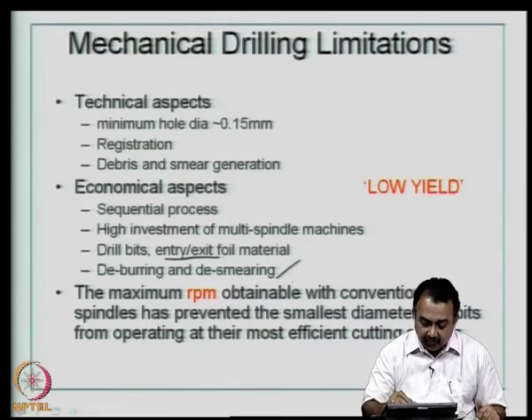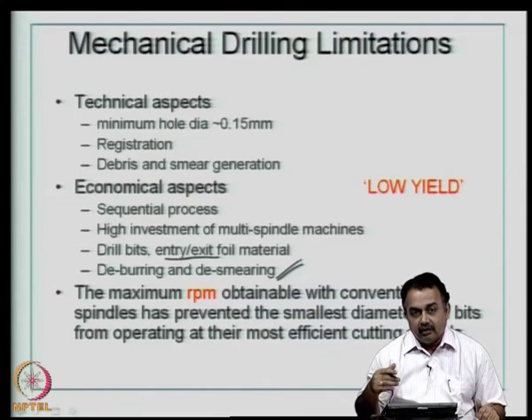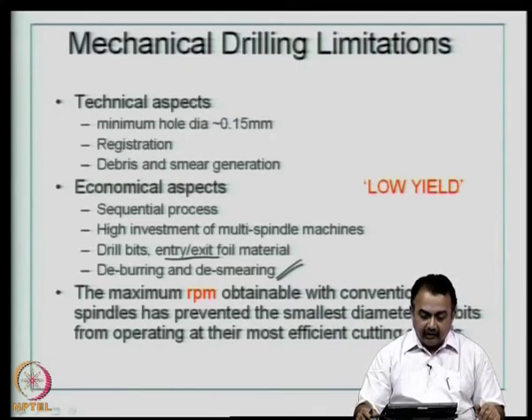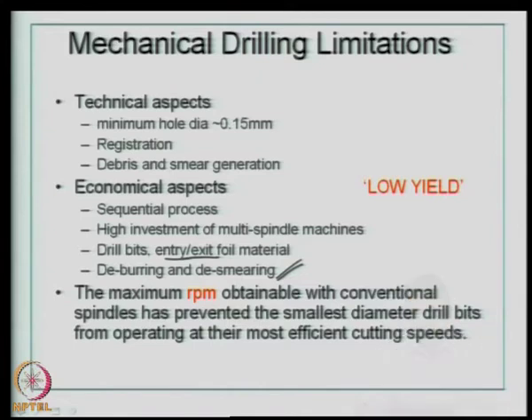Deburring and desmearing is a very important operation to remove the debris and to prepare the hole wall conducive for electroless plating. And the maximum RPM obtainable with conventional spindles has prevented the smallest diameter drill bits from operating at their most efficient cutting speeds, which results in breakage of drill bits and so on. So, we will now look at in the next class a comparison of all of these various methods to create microvias and look at how actually you build high density interconnect structures from a given core substrate.